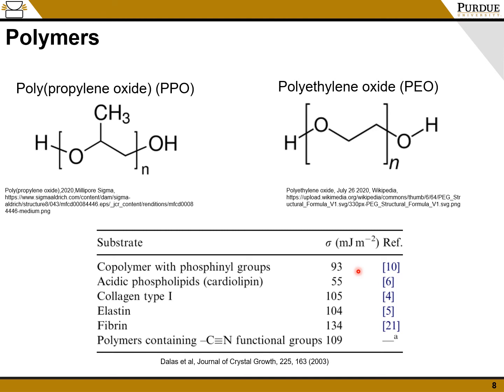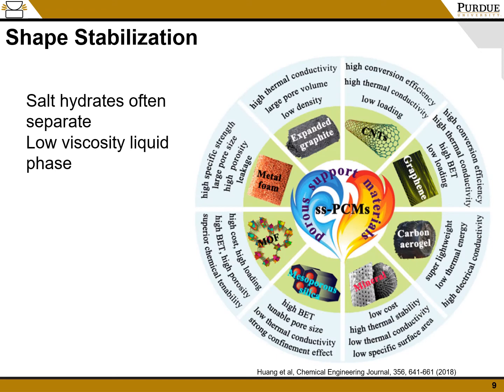to start nucleation. The most promising one of these all is ones that contain the cyanide functional group, because while this does have a polar property and interacts with these metal cations in the salt, it does not have interaction with water, which is very promising. Phase separation is a significant problem experienced by salt hydrates. They often separate and the salt precipitates out of the solution. This reduces the number of thermal cycles a PCM can be used for.